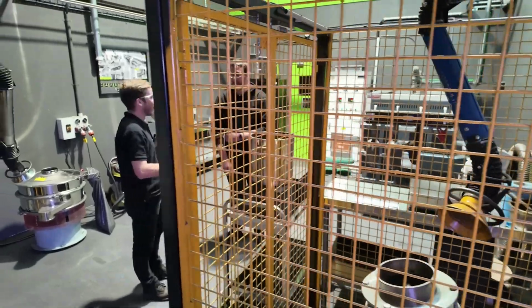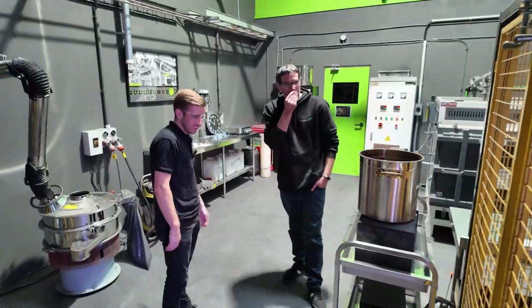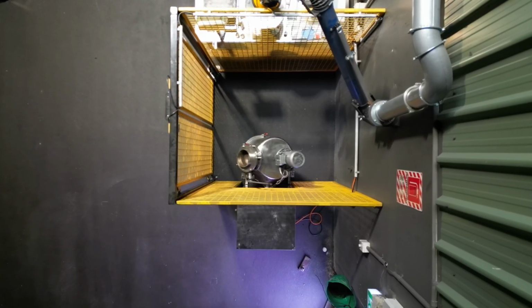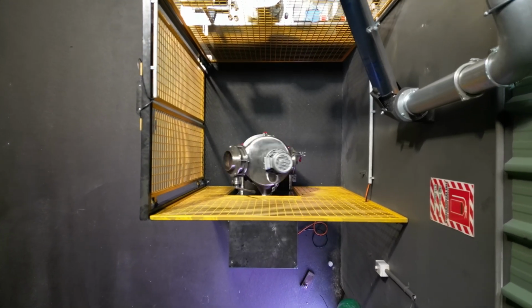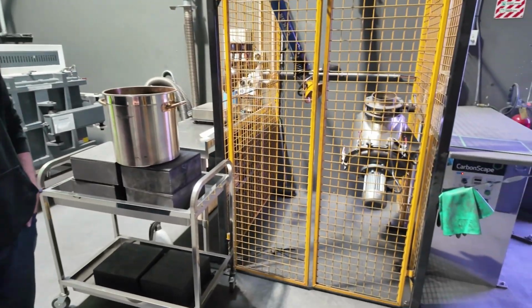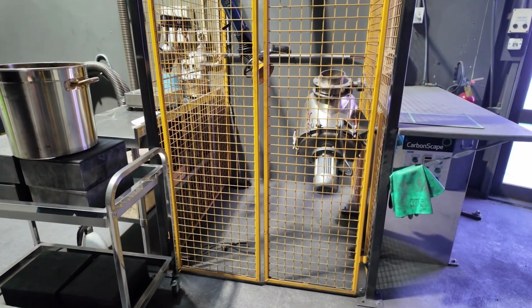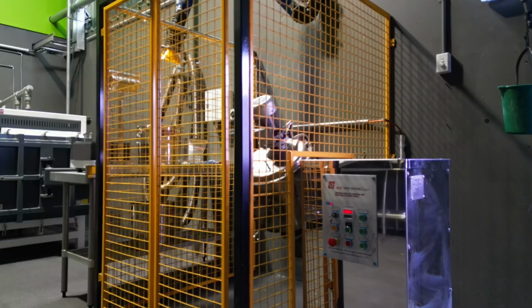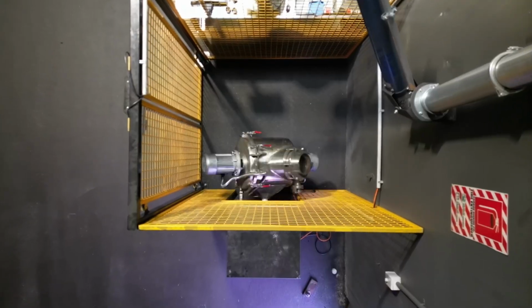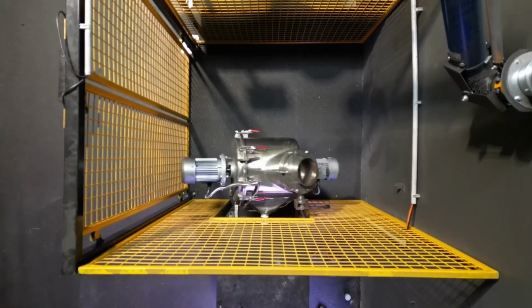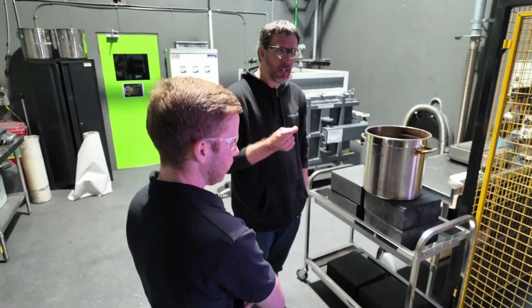The next step is coating, one of the most important stages in producing anode material. CarbonScape applies a controlled carbon layer to each graphite particle, stabilizing the surface and improving the initial Coulombic efficiency. Coating reduces irreversible capacity loss, protects the particle during cycling, and helps form a more stable solid electrolyte interface.